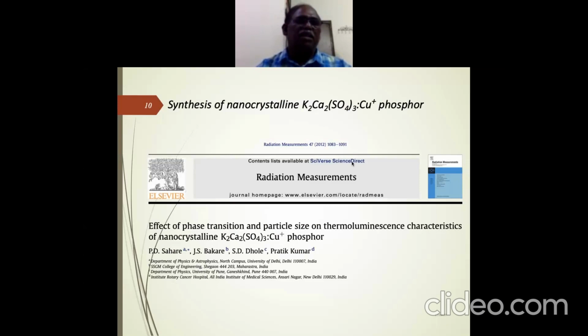In the literature, we found some papers where just by simple co-precipitation methods you can synthesize nanocrystalline materials. My first paper on this was on nano CaSO4:Dy, which is a well-known TLD material for measurement of radiation. We found that when you go down to the nano size, the sensitivity of this material to radiation by the thermoluminescence technique decreases.